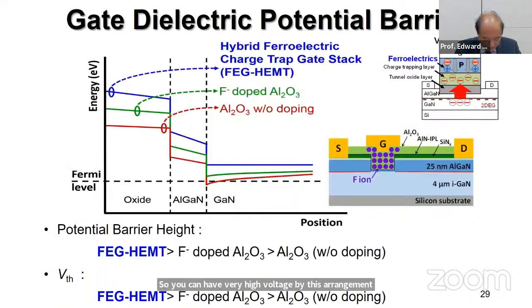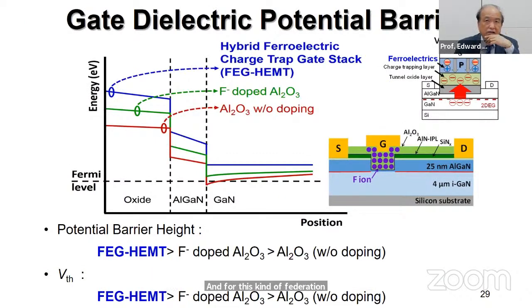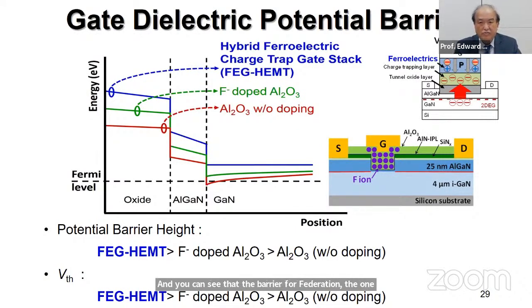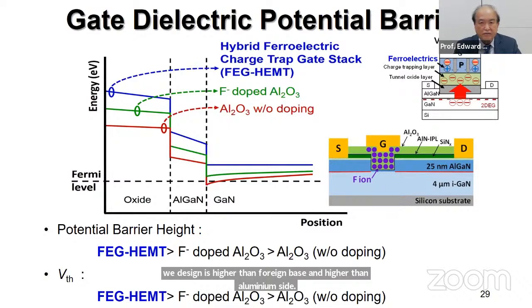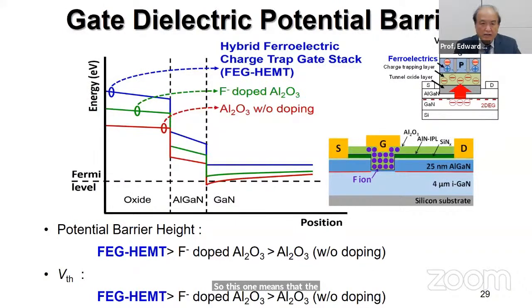And for this kind of ferroelectric material, we can see the gate dielectric potential barrier, and you can see that the potential barrier for the ferroelectric gate, the one we designed, is higher than fluorine-based and higher than aluminum oxide. So this means that the ferroelectric gate we designed has a higher VTH than other approaches.